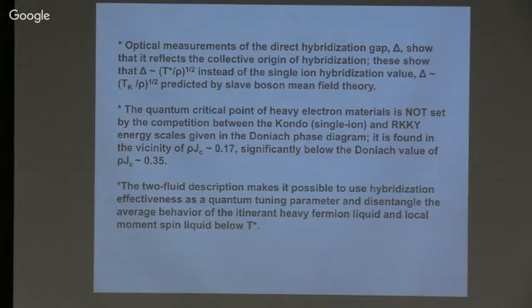The optical measurements show that the so-called hybridization gap, a gap that you see optically very well, depends on T star, not on T_K. And the quantum critical point then is not set by a competition between single ion and RKKY energy scales. It's found at a much lower value of J, of the order of 0.17. And the tuning parameter for all of this is the effectiveness of the collective hybridization.